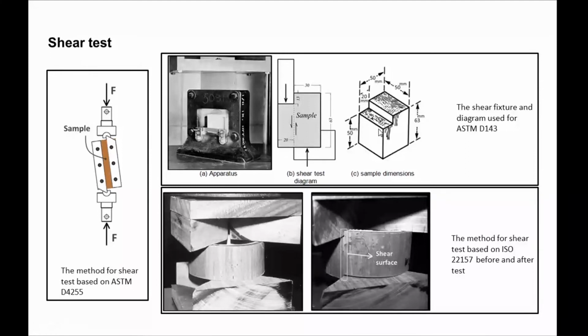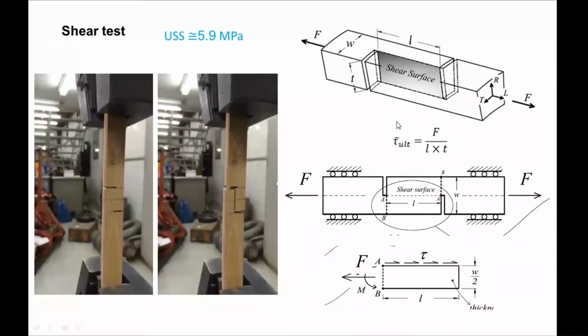But as our geometry is very limited and we cannot make a block of bamboo because of the limitation of the wall thickness of the bamboo, we need another method, proposed by ISO 22157. You put the sample like that, with 2x here and x here, and you can have 4 shear surfaces in 4 different locations, and you can measure the shear resistance of the bamboo. We propose another way, using 2 notches here and here, and we have a shear surface here. With this shear test, we find 5.9 megapascal for these samples.